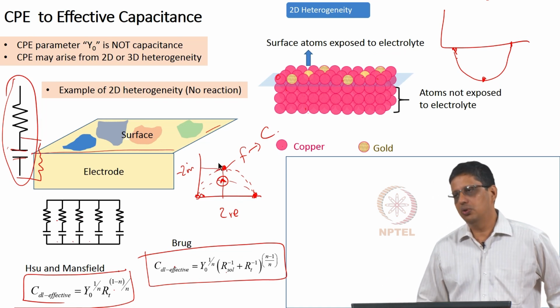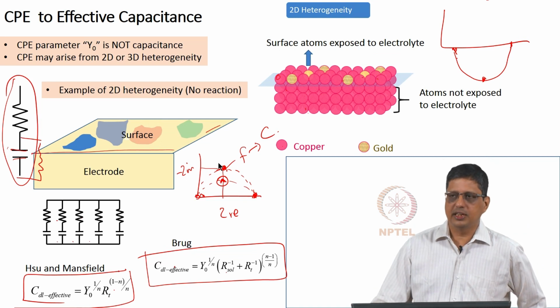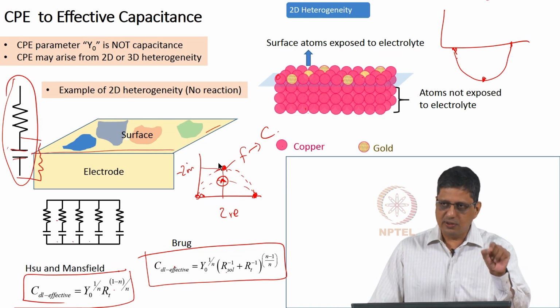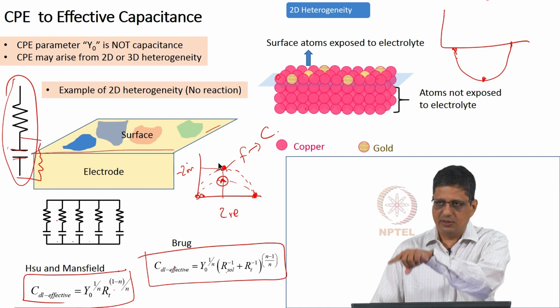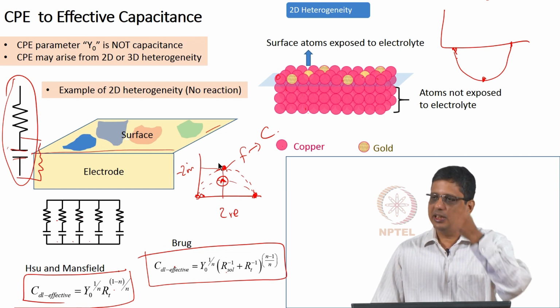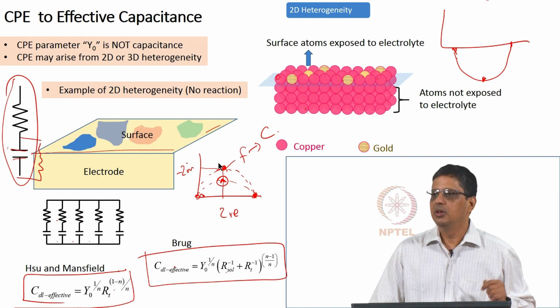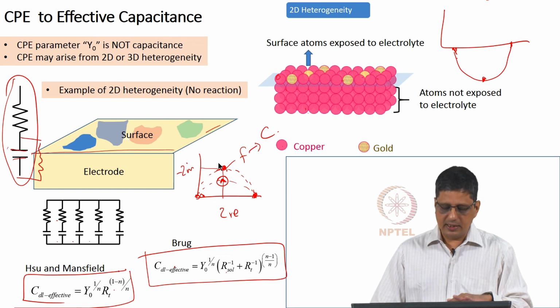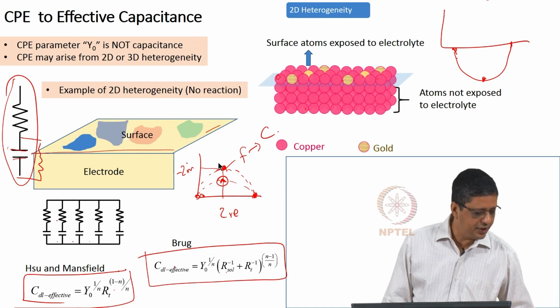Of course, now we do not do this, right, we can fit it using a software. Previously what people would do is, when they do not have access to such programs, they would plot it, get the R solution by extrapolating in the graph, get the RT by marking where these points will go, and then go to the center meaning the peak value, note which frequency that point is, and from that they will calculate the capacitance. Now we would use the software, use optimization and then get the value, because we can fit it to many types of circuits, but this is the origin of this equation.